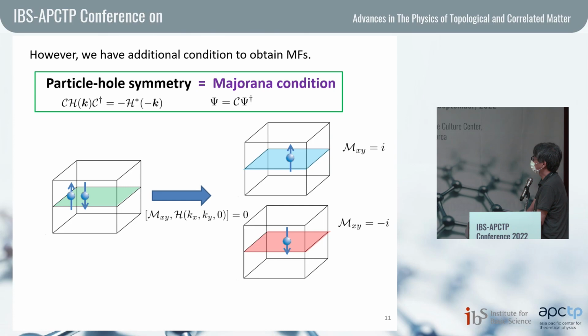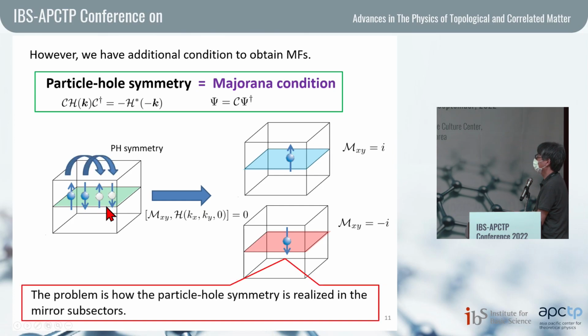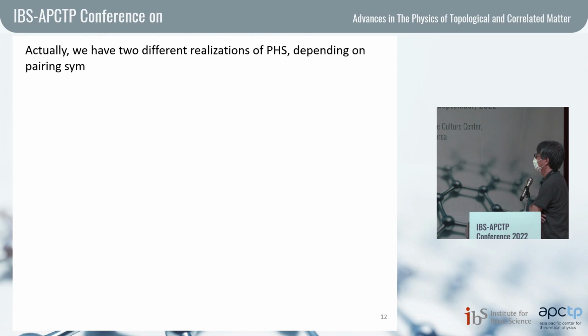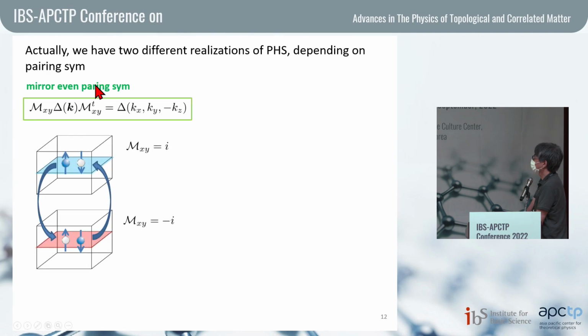So in the superconducting state, in addition to the up-spin electron and the down-spin electron, we also have the up-spin hole and the down-spin hole, and they are related by the particle-hole symmetry. So the problem is how the particle-hole symmetry is realized in the mirror subsectors. And actually, we have two different realizations of the particle-hole symmetry depending on the pairing symmetries. For example, let's consider mirror-even pairing symmetry. In this case, the gap function is invariant under the mirror reflection symmetry. So the mirror reflection symmetry is trivially realized in the superconducting state. In this case, we found that the particle-hole symmetry is realized in this manner.